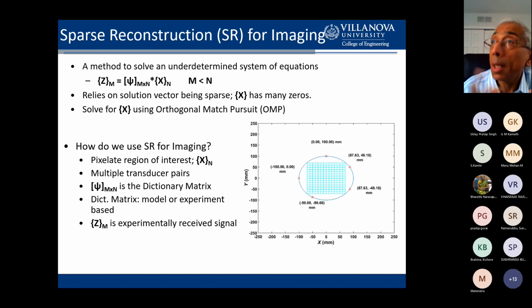Your structure is healthy, but occasionally a defect can arise. When that does happen, there are very few of them. So only 1, maybe 2, maybe 3 of these cells is populated with a defect. The other cells have no defects. A defect could be in, for instance, the top left cell over there, and that's it. Every other cell has no defect. If a defect is present in a cell, you assign the number 1 to that cell, and if a defect is not present, you assign a number 0. Then you would have what's called a very sparse grid. Only one of the cells has a 1, and the other cells are all 0. That essentially functions as my x unknown vector. Lots of zeros and just 1 or 2 ones, and I just don't know where they are, and I'm trying to find them. That is my x vector.